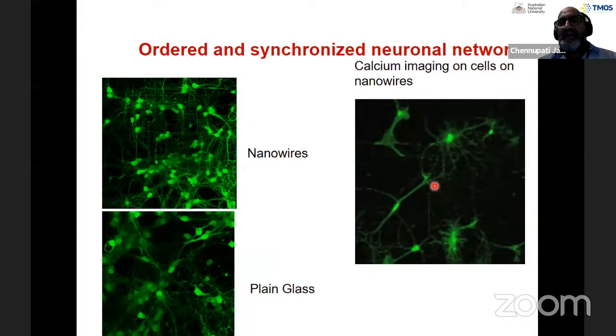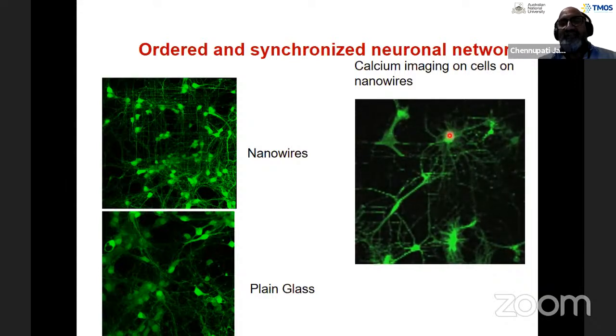So what Vinny does is something called calcium imaging. In the case of calcium imaging, she puts in a calcium dye. As and when the neurons are firing action potentials and opening up the ion channels, calcium ions are passing through, and the calcium ion concentration will determine the fluorescence intensity, in the calcium imaging technology which people use. Then she does the correlation maps. If this neuron is firing, what's happening to this neuron and this neuron and these astrocytes, to really study what type of interaction is taking place. So she tries to compare neurons grown on nanowires and also neurons grown on plain glass substrates.